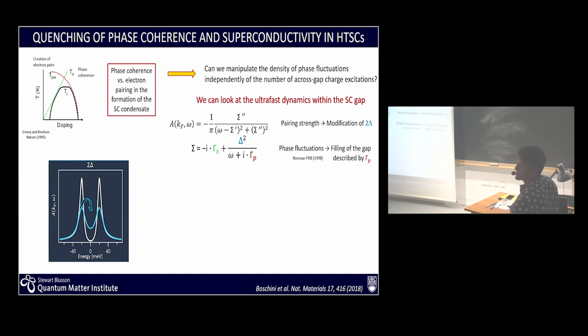And yes, gamma p is the pair-breaking. Gamma s is a single particle scattering rate, which is also there. However, at low temperature it won't play much of a role, so that is not going to be changing. But it is also there in the system. So when you do an analysis of a spectral function, you would start off with an analysis above Tc, which allows you to define the gamma s, and then you go below Tc, and now what we can show is that much of the action is in the gamma p. And in fact, even the work done by Luca and others show that once you go below Tc into the superconducting state, much of the action is in the gamma p.